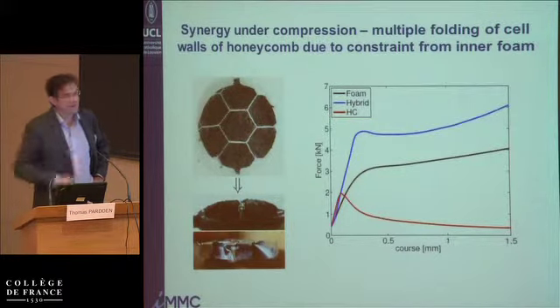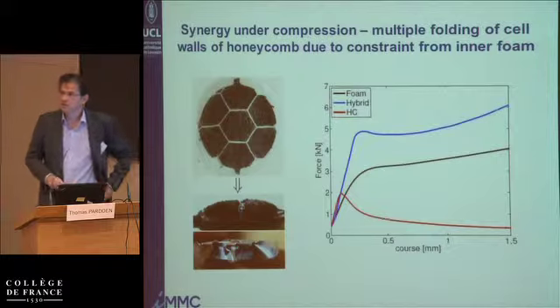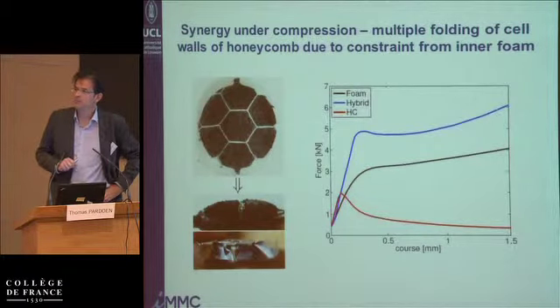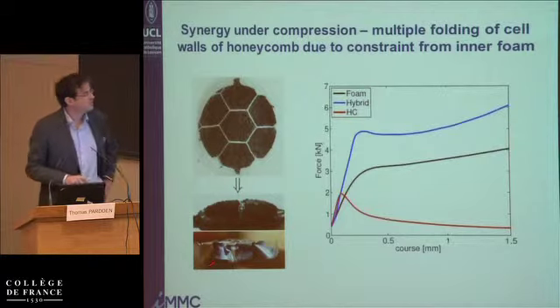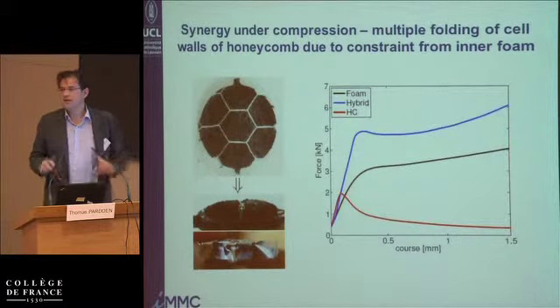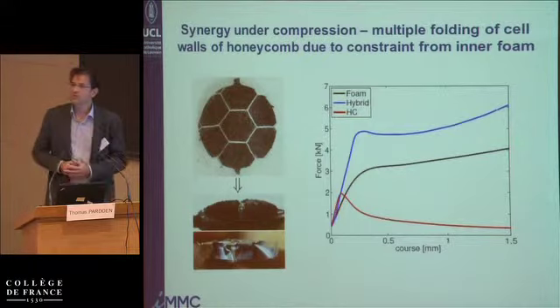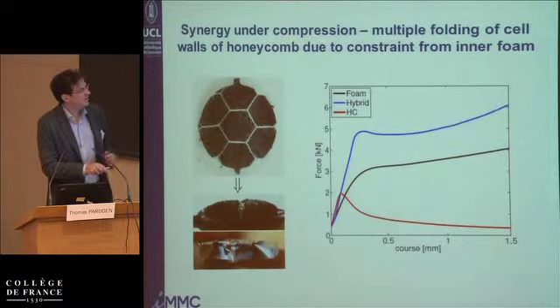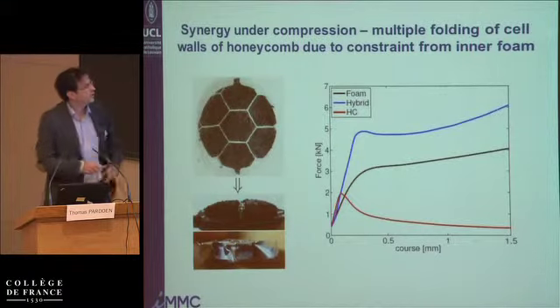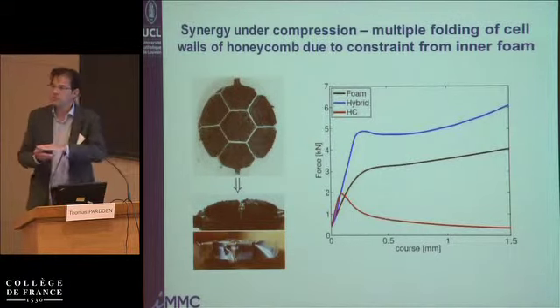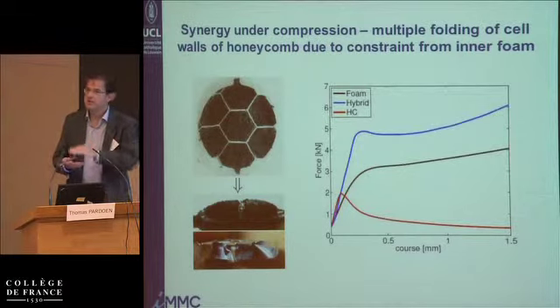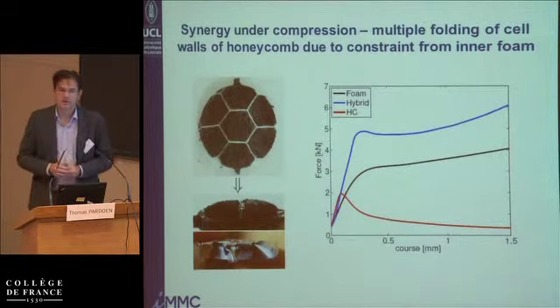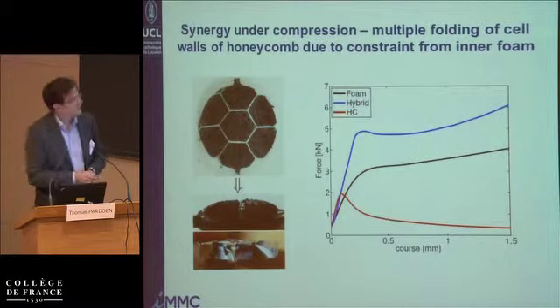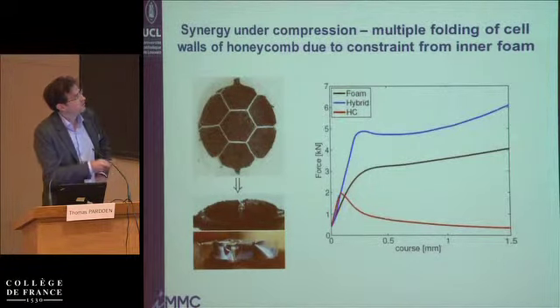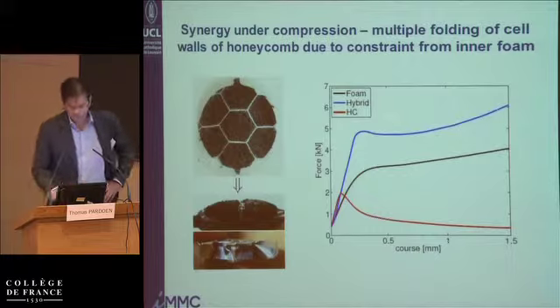We have been lucky to see that the presence of the foam inside the aluminum honeycomb plays a very interesting role in distributing the load and constraining the faces of the aluminum honeycomb. Instead of having a single buckling mode during compression, we're getting a multiple buckling mode. So much more mechanical energy is dissipated during the compression of this honeycomb when there is a foam inside. And these are the compression curves for the honeycomb, just the foam, and the synergy of the two.